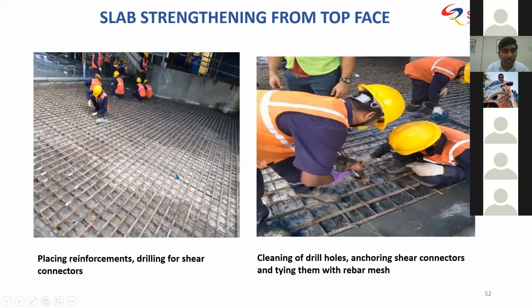And just putting this mat there is not enough. This has to be mechanically bonded to the existing concrete. How do we do that? By using L-shaped shear keys. So you can see here, drilling of holes had happened. Here they are tying the rebar. Actually, the drilling is not shown.